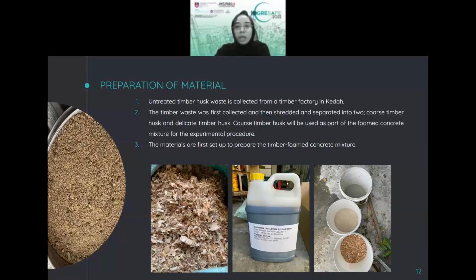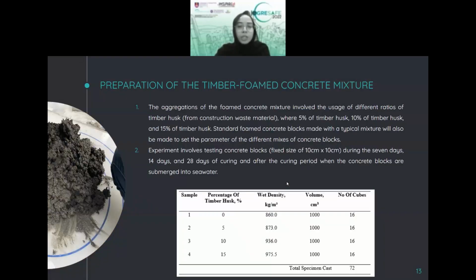So coming next is the preparation of the timber foam concrete mixture. Afterwards, I will come to the preparation of the mixture where 0, 5, 10% and also 15% of timber husk is used. The experiment involved testing concrete blocks of fixed size on the 7, 14, and 28 days of the curing period, and after the curing period, they will be submerged in the seawater.